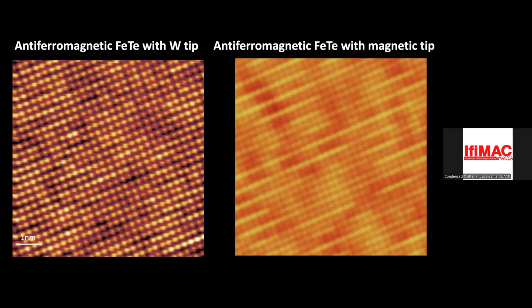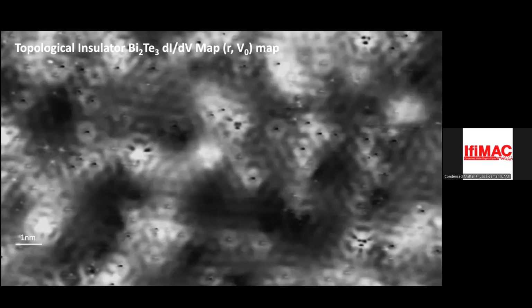And this is an example of the other end member of the series, iron, selenium, tellurium. One end is a superconductor. When you add tellurium to FeSe, you also get a superconductor. By the time you get to the other end, it's an antiferromagnet. So this is imaging the tellurium atoms on FeTe with a normal tip. But then if you have a magnetic tip, you can see these stripes. And these stripes are basically the antiferromagnetism at the atomic scale.